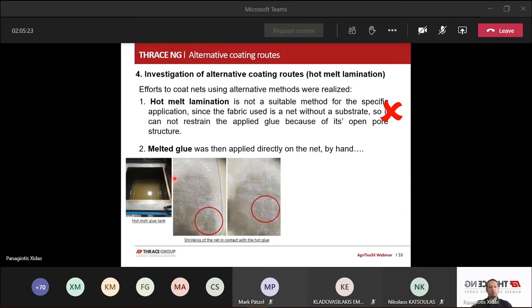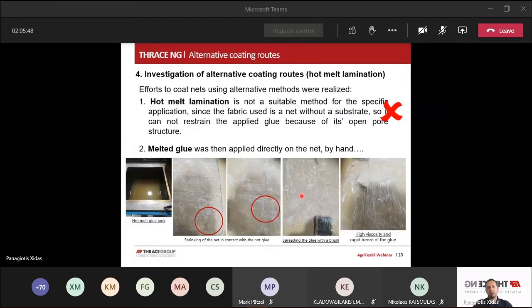So when the glue was poured on the net, instantly it was causing shrinking of the net. I don't know how clear it is in these images, but these are the areas of shrinking of the net. Another problem using the brush was the very rapid cooling down of the glue. The glue was cooling down so quickly that we couldn't spread the glue all over the net. You can see also here the direction lines formed on the glue by the effort of spreading the glue. Of course, the result is not good, and this effort was not very successful.